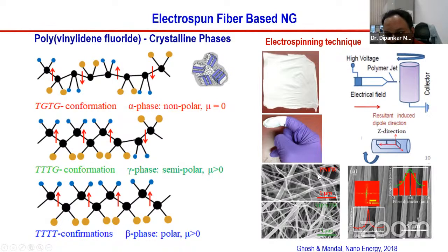But in some cases, if you need a random fiber, then you can reduce the RPM, the rotation speed, or simply place a metallic collector, a static, fixed collector. In that case also we can collect random fiber. These are the SEM images of the random fiber. This is the oriented fiber. And this is the real photograph, the white one. You can imagine it has very good shape-adaptive properties and is air permeable in nature.